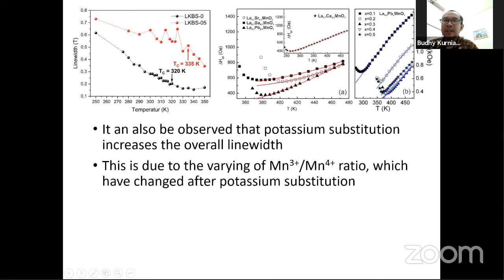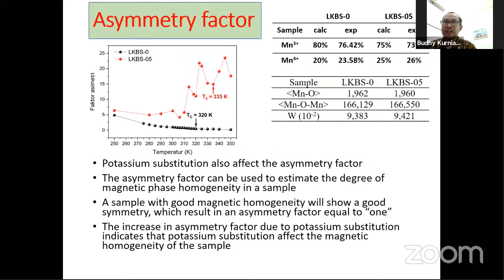And the variation of the ratio of manganese 3+ and manganese 4+ also contributes to the line width of the ESR. As for the asymmetry factor, the increase in asymmetry factor due to potassium substitution indicates that the potassium substitution affects the magnetic homogeneity of the sample.